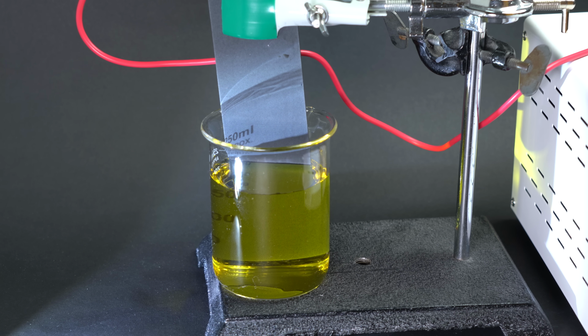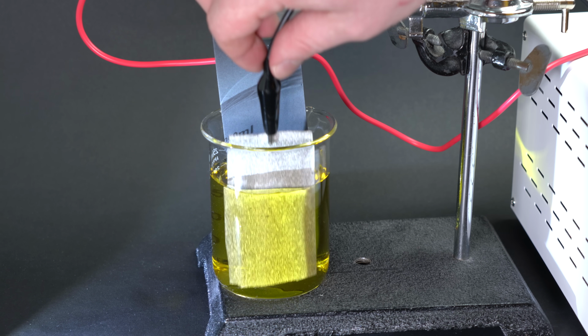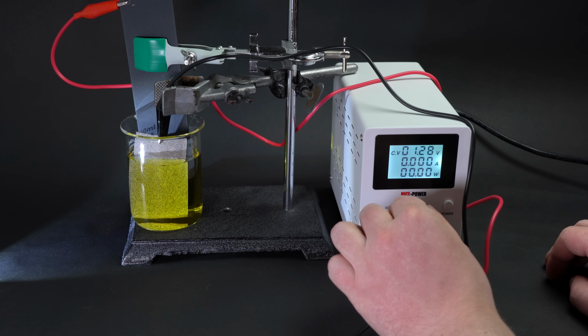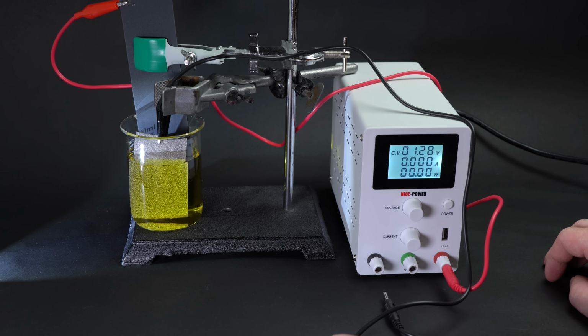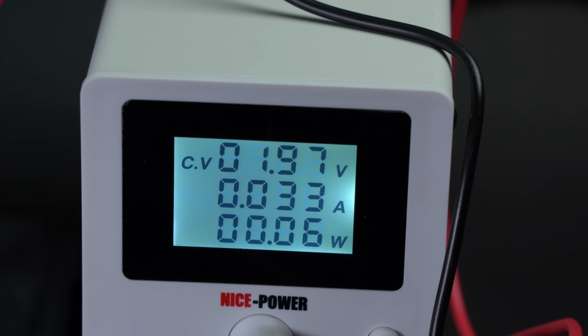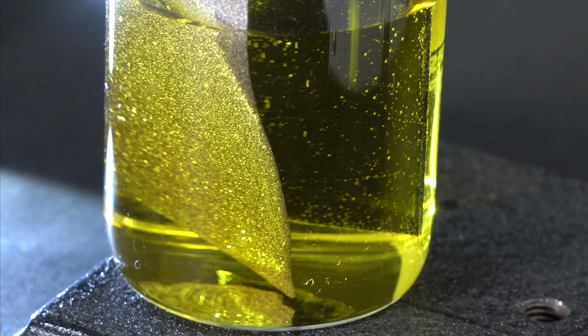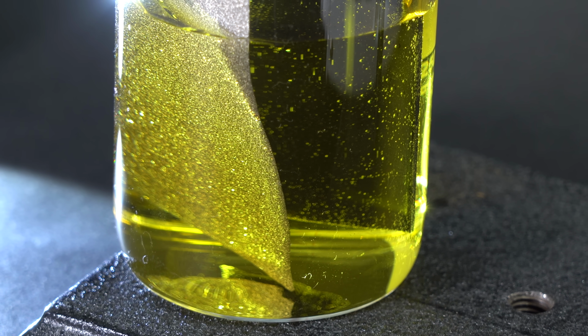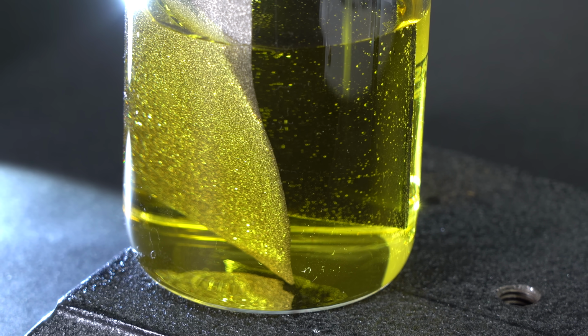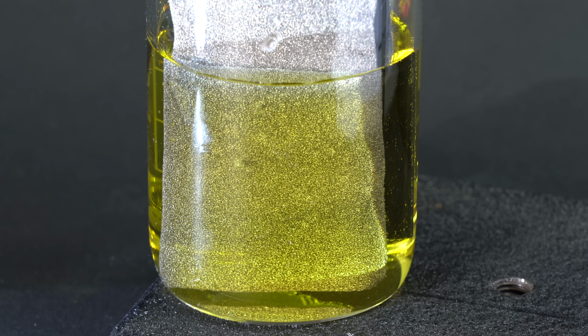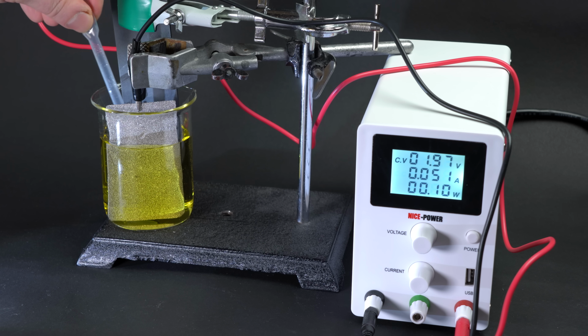To do platinum plating, I'm lowering a purified nickel sponge into the solution and starting to run electricity through it using my laboratory adapter. During this process, platinum is slowly covering the surface of nickel, creating a very thin gray layer because of its slightly grainy structure. It took me 20 minutes to cover one electrode with platinum.